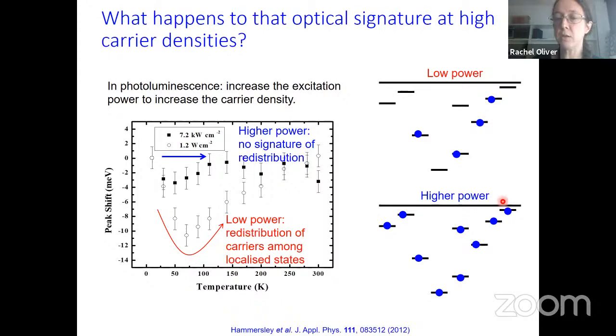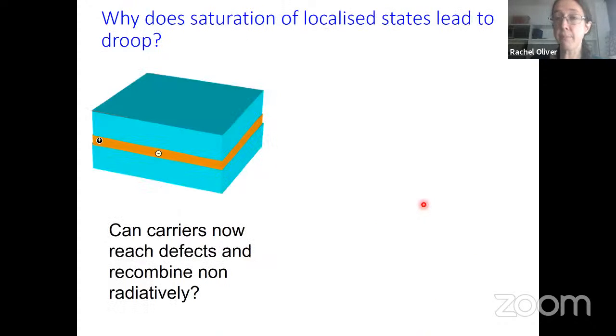But at high power, we don't see it, not because the localized states are gone, but because we've filled them all up. There's no spaces left in the localized states. And if we keep adding more and more carriers, they may end up in the quantum well, but they won't end up in those low energy sites. So if we've saturated the localized states, that may well mean that the carriers can now move through the quantum well, no longer trapped by those high indium content regions. They can reach the defects and they can recombine non-radiatively.